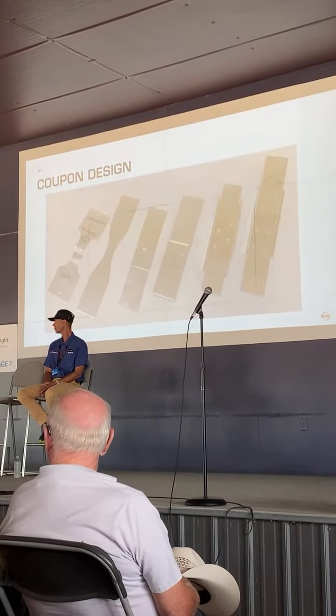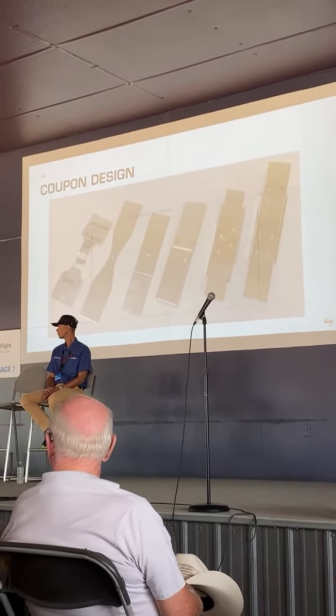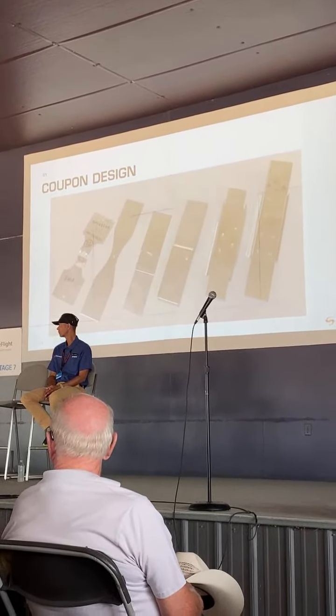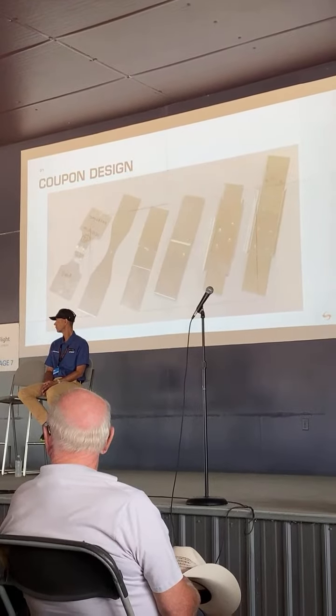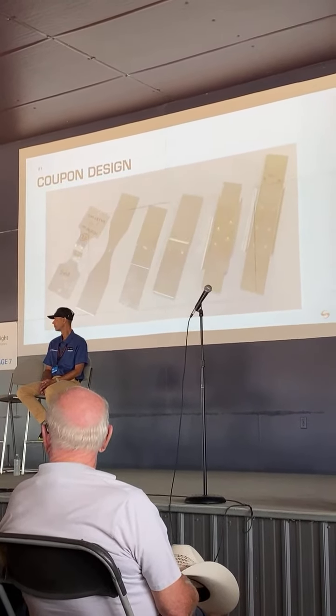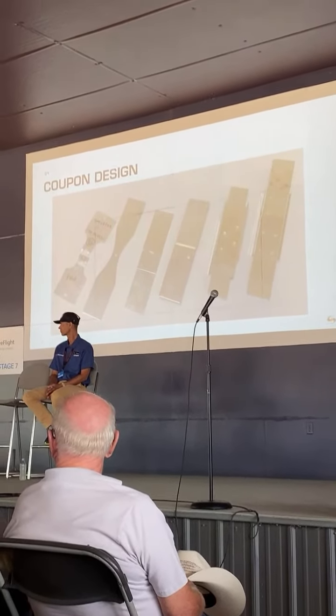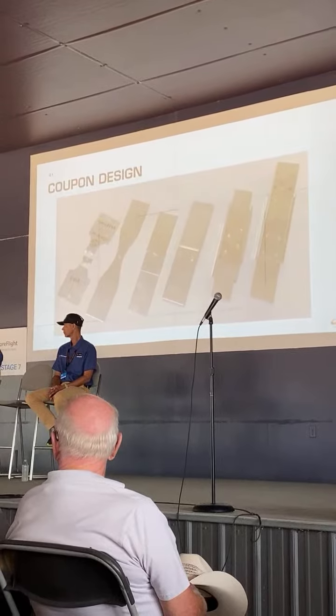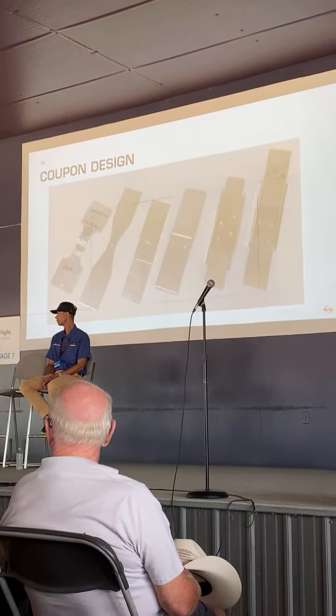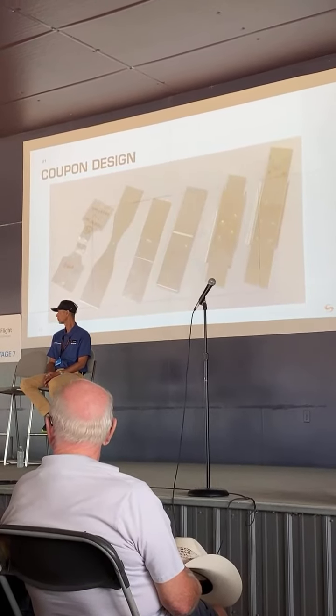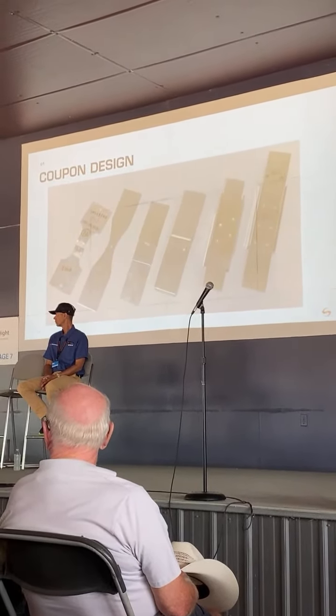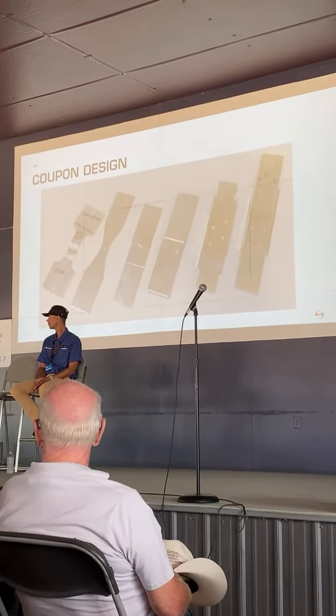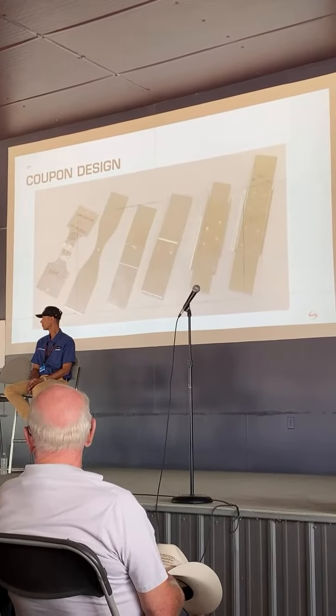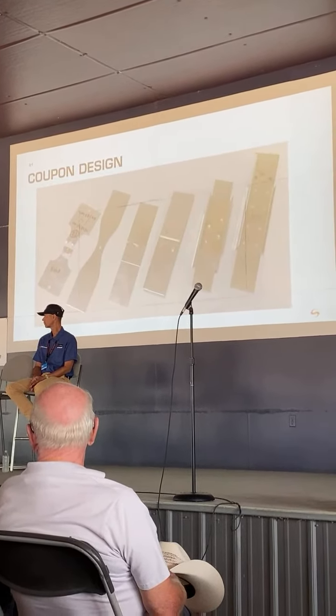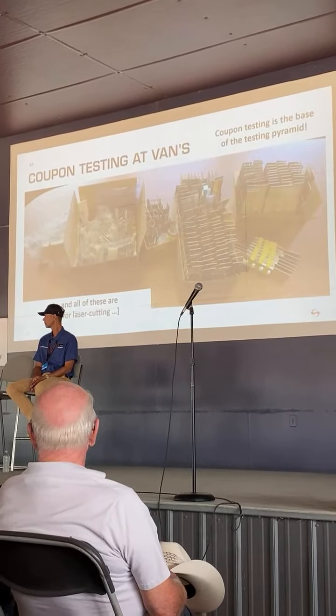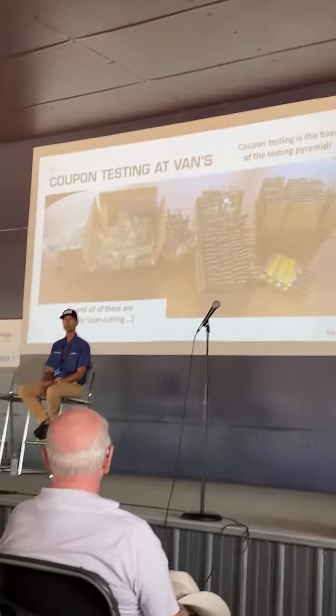There are different types of loadings. There's somewhat peel load, where the skin is peeling up against the rivet, and in that case you would most likely fail the edge of the dimple, or even sometimes the dimple die mark fails before the hole itself. And then there's the case where you have a skin against a solid member, and more of the load goes into shear. So instead of peeling the parts apart, the load goes directly into the rivet against the edge of the hole. And that's what you see on the right side of those specimens. We have thicker material in the center of these specimens that make sure that the load is going into shear inside the rivet. Just an example of some of the coupons we've tested.